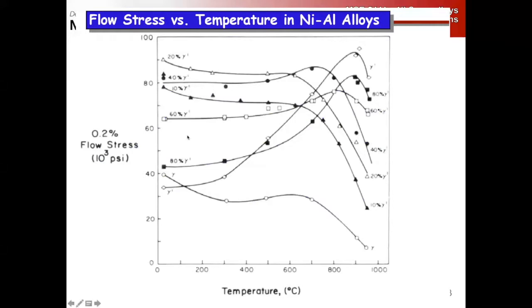But this is not all the same exact composition. And so what difference the initial strength is as a function of composition versus a function of gamma prime fraction, you can't necessarily deconvolve those. And also the alloying elements will have a significant effect on the strengthening, because you still have the solid solution strengthening effects in the gamma prime as well. Depending on where the gamma prime partitioning elements are, are they on the nickel or aluminum sublattice, how sensitive they are. Some alloying elements don't care which sublattice they're on. Others have very strong preferences.